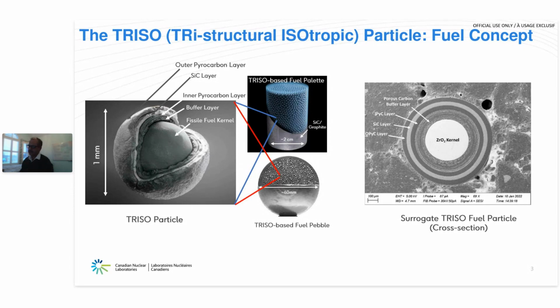The image on the extreme right that you see is basically a cross section of our TRISO particle showing different components of the particle itself. It's called surrogate because the kernel here is zirconium oxide instead of nuclear fuel, which is typically uranium oxide. And this is done for developmental purposes. Like, so life is easier when you start simple.